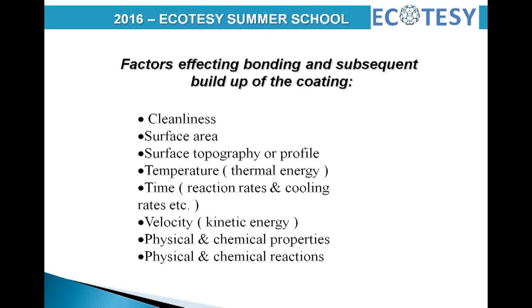High kinetic energy thermal spraying using HVOF and cold spray procedures gives high bond strengths due to energy liberated from high velocity impacts. The high density tungsten carbide cobalt and cold spray coatings are good examples. Metallurgical or diffusion bonding.